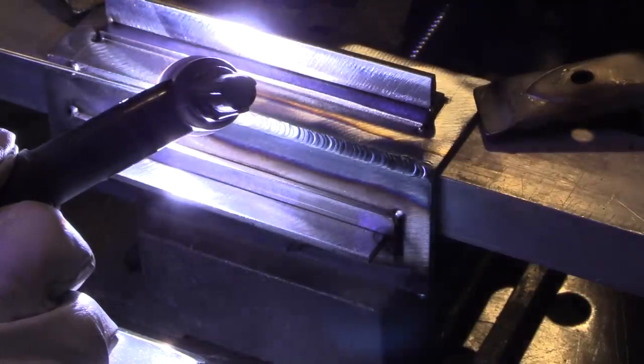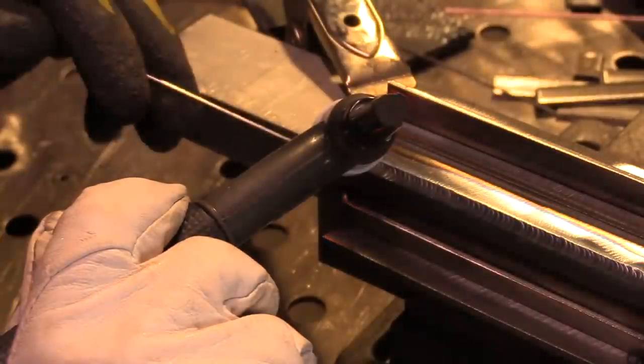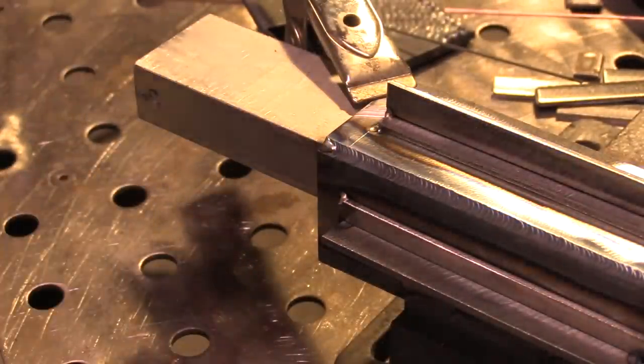Let's take another quick look at that arc shot and talk about the hot tip of that rod. You can see how I'm not coming very far out of the puddle. I'm keeping the hot tip of that rod shielded with the argon envelope coming out of that number eight cup. That's important. You can get away with it here and there coming in and out of the argon. You'll notice a difference when you introduce that rod back into the puddle, but you don't want it. You don't want to make a habit out of it. You want to keep the hot tip of that rod shielded, keep those oxides out of the puddle. Otherwise the puddle swims around and it's kind of unruly. We're tapering off here. I'm taking two to three seconds to taper off, backing up a little bit as I do. I'm going to hold the post flow over there and let it time out.